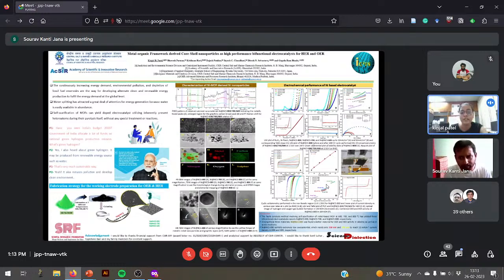The electrochemical performance is evaluated using linear sweep voltammetry. The overpotential parameter shows that the material at 800 degrees has the lower overpotential, which also compares with the benchmark catalyst, ruthenium oxide, at high current density. The Tafel kinetics, which is obtained from the Butler-Volmer equation, shows that the material obtained at 800 degrees has excellent electrocatalytic activity. For the durability and stability test, we performed cyclic voltammetry and the chronoamperometry experiment.